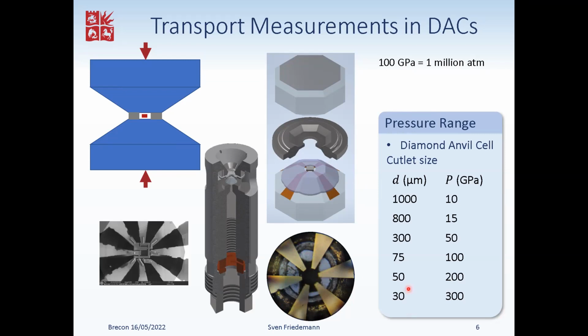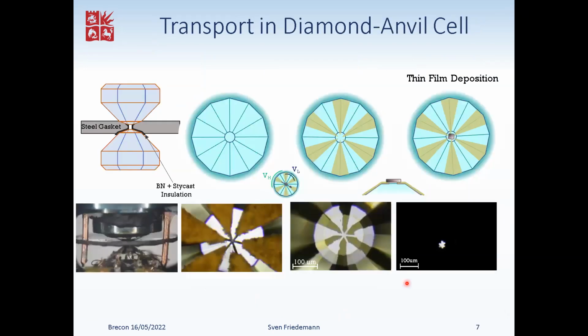But if one wants to go to pressures relevant for hydride research, we need to go to culet sizes of about 50 micrometers. And this dictates that samples cannot be more than 25 micrometers in size. Okay, so how do we make these electrodes? Mostly we do this with a masking technique.